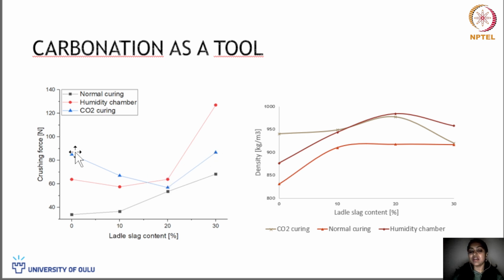It is assumed that the CO2 curing carbonates the ladle slag on the surface of the granules, and once the pores were closed by calcium carbonate products, there may not be carbonation happening after that, as there is no porosity anymore on the surfaces. So the interior part of the granules is not accessible by the CO2 once the porosity is saturated or the pores are closed by the carbonation products, whereas humidity is not happening in that way.